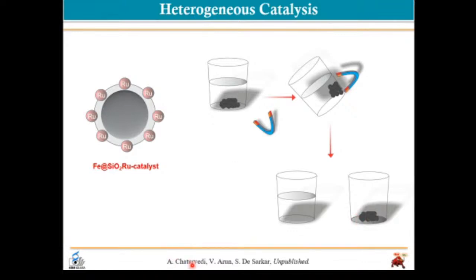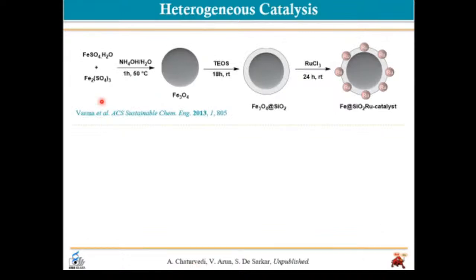And one talented master student who worked in my group, Ashwin Chaturvedi, is now doing a PhD in the US. He did this last year. He took this iron 2 and iron 3 combination to make the iron nanoparticle. Actually, we are not the first ones. He followed the reported literature for preparing this catalyst. First the iron ball or iron nanoparticle, then he put this silica bed, a kind of silica glue, on this iron ball, and the ruthenium trichloride catalyst is embedded on this silica bed. As a whole, it becomes a very good nano catalyst, an insoluble heterogeneous catalyst.